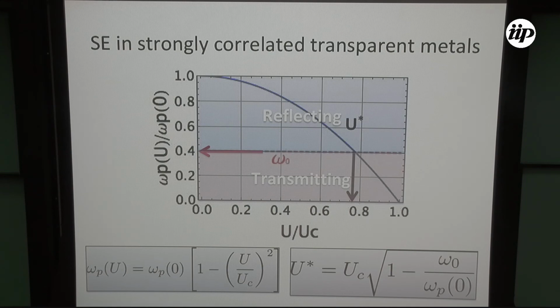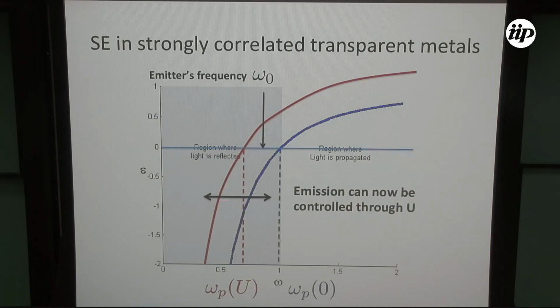I put an emitter inside the material, and I see when it emits light. This is controlled by interaction. So this is another way of looking at what I've just said. The blue line is the bare plasmon frequency. The red line is the renormalized, strongly correlated plasmon frequency. And for an emitter that is in between, you can control U, making the red curve go to the blue and go back again. And then you can have transparent and reflecting versions of the material.